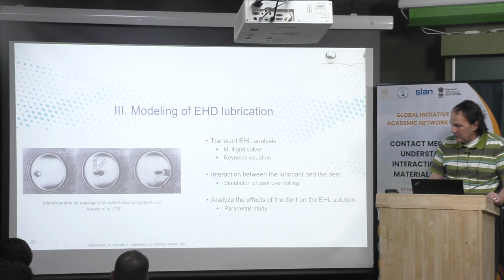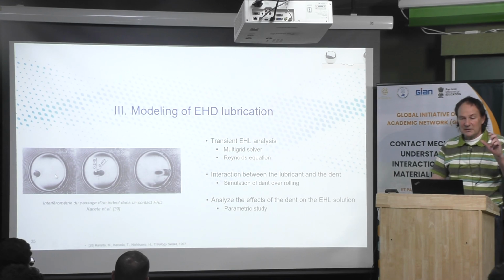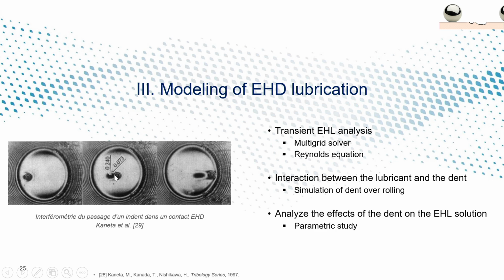Within it you have some oil, which is pressurized at very high pressure, in a glassy state. Because the pocket of oil is moving at the mean speed between the two surfaces, it is moving to the rear of the contact, because it is moving slower than the dented surface, and you can see that there is a second dent that appears due to that. This is exactly what I said before.